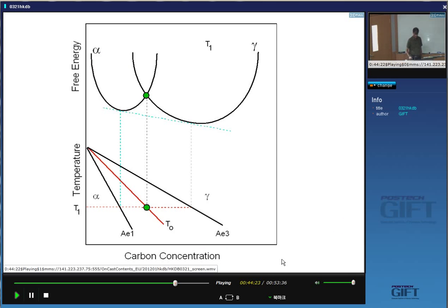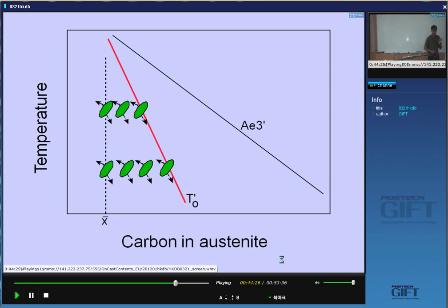So I'll illustrate that once more. Right, so if it is the case that bainite forms like martensite but the carbon then escapes, then the reaction would stop at the T0 curve. Okay? This dashed T0 simply represents a calculation where you take account of strain energy. But if carbon partitions during the growth of bainite, then you can see it's a big difference. These are real calculations. And the difference between this concentration and this is very large.